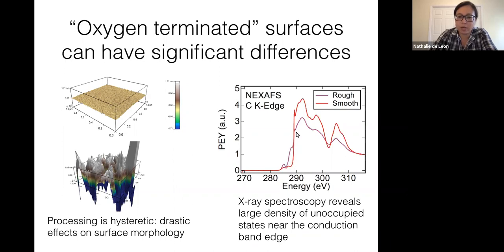So what you're looking at here is the unoccupied states. Everything that is to the right of this exciton peak is the conduction band structure in diamond, and everything that's to the left shouldn't be there because it's a mid-gap defect state. And this rough surface has this giant forest of mid-gap states that are entirely just related to this morphology.